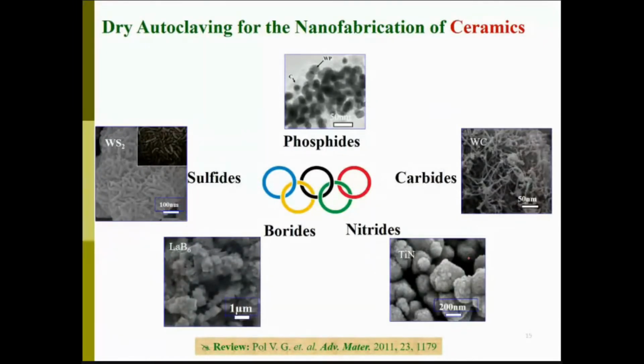So this unique process made almost everything from the periodic table, and that is the reason I was highlighting some of the elements in the periodic table, where we could make very unique sulfides, tungsten disulfides, which is a very nice material for lubrication. One can make phosphide-based materials, which are very stable. The tungsten carbide-based materials typically can be prepared around 1600 degrees Celsius, but in this particular case, it required only 800 degrees Celsius temperature. And the reason was you start playing with the atoms where a small amount of energy is required.